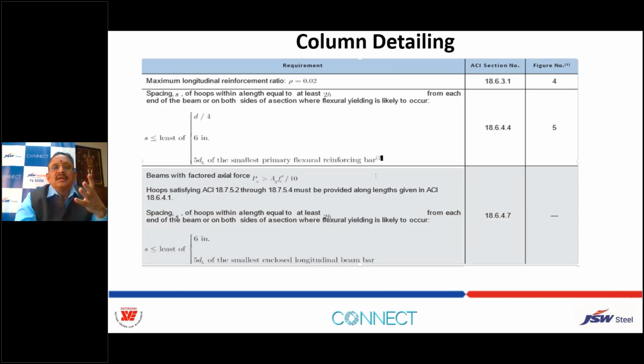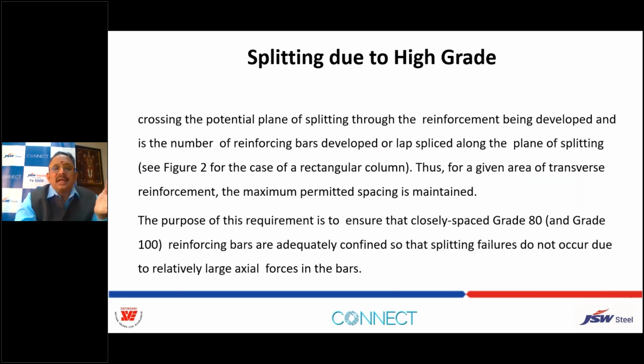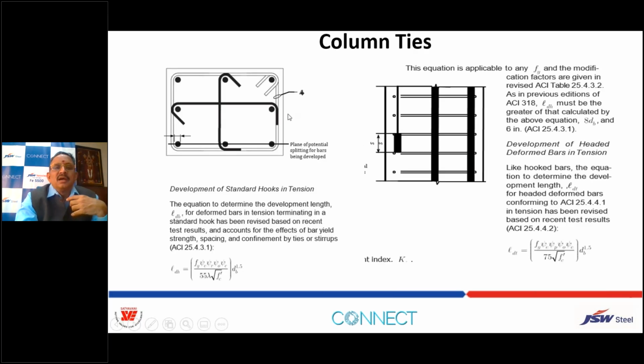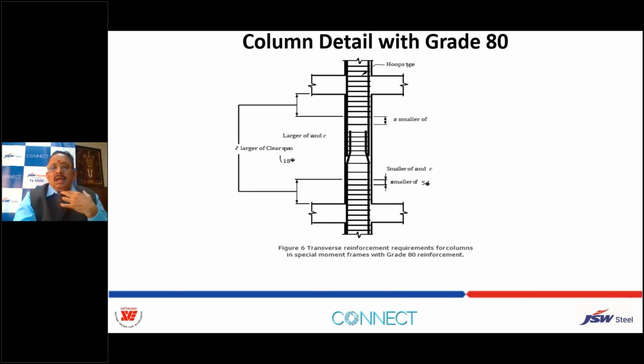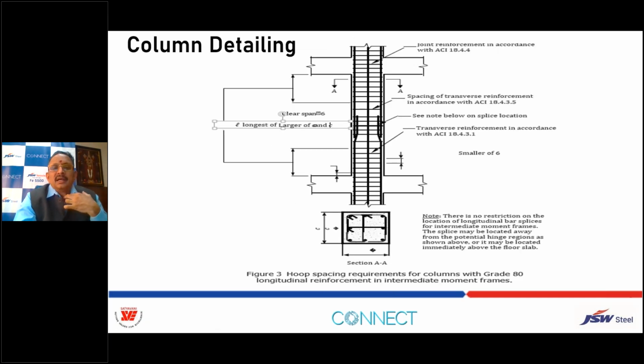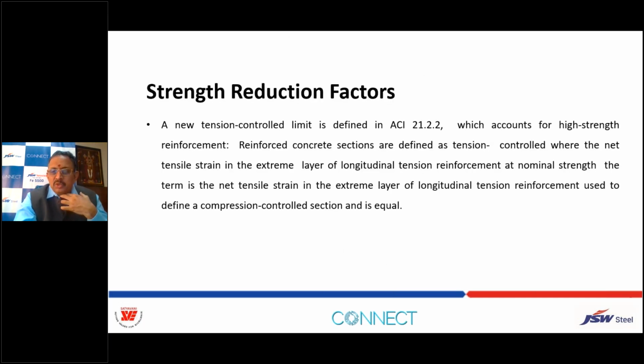The column detailing, when it comes to splitting due to high grade, you have to follow this ties provisions and the spacing of these ties, all that, depending on the diameter of the bar and splice, these anchors, mechanical anchors, all this. So this is the position of the splice, and this we have to follow 13920 anyway for the shear calculation and ductility provisions. And ACI also gives all these provisions for high strength bars. When we use the high strength bar, we have to utilize this.